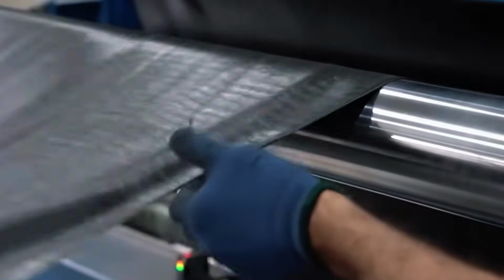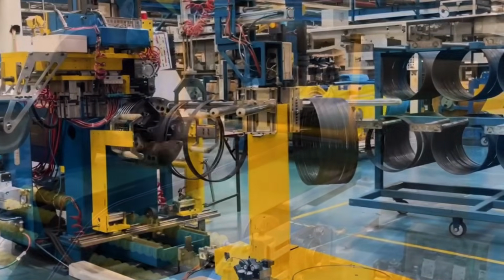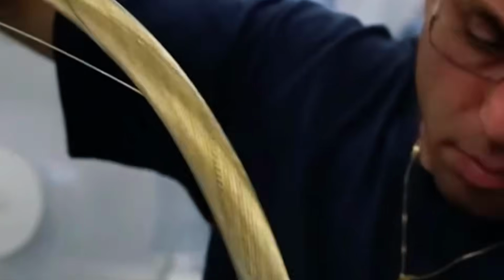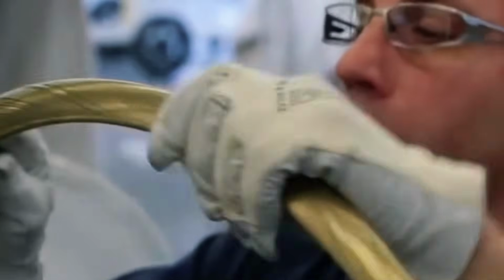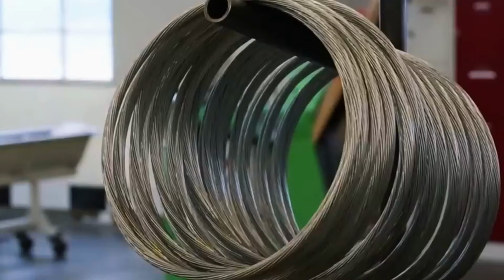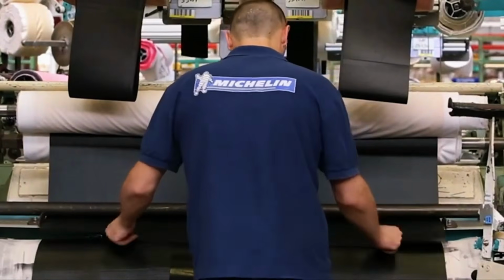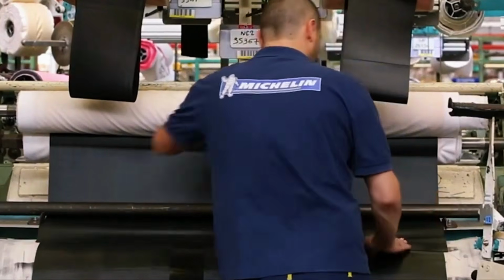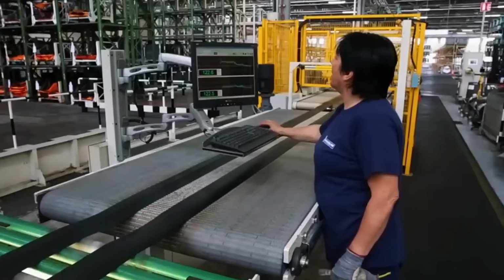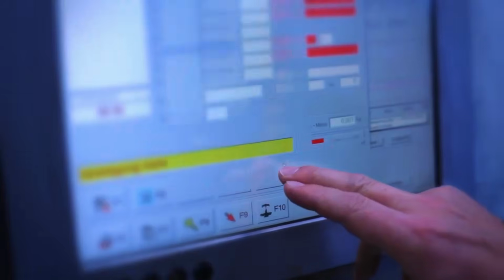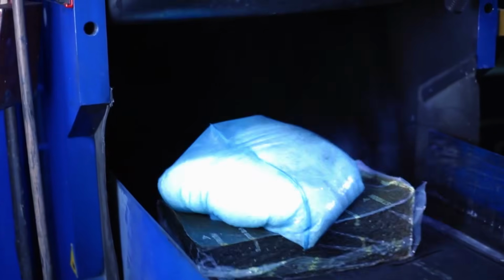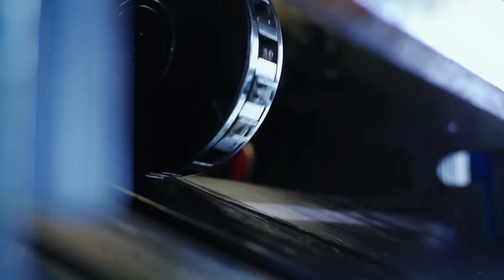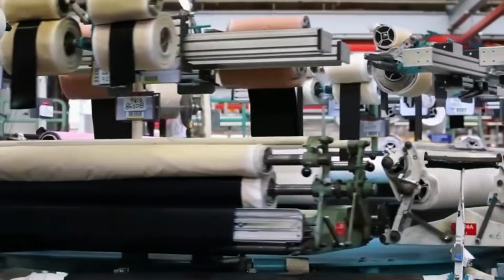The real strength of an aircraft tire comes from what is hidden inside it. Inside every aircraft tire, completely concealed beneath the rubber, is a structural skeleton that most people never know exists. The reinforcing fibers are typically high-strength nylon or aramid, the same class of material used in bulletproof vests. These fibers are woven into dense technical fabric sheets with exceptional tensile strength relative to their weight. Before use, the fabric passes through a rubber coating system where heated compound is pressed into every individual fiber under high pressure. Every fiber must be fully encased. Any uncoated fiber is a potential failure point.